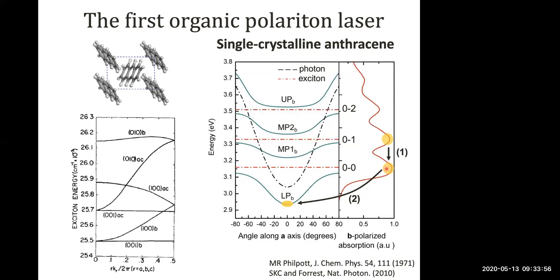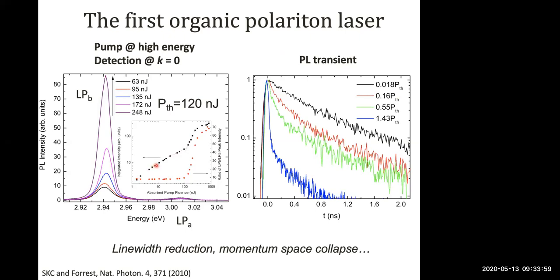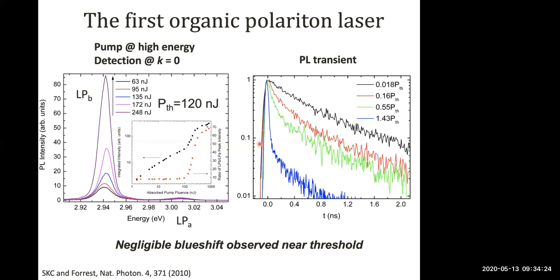And then when you pump the system at high power, you find this threshold from a sublinear regime, just because you have very, very strong bimolecular annihilation, to a superlinear regime, as well as a collapse in line width, a collapse in the k-space distribution, and a collapse in the lifetime once you cross threshold. An interesting feature in anthracene, which is rather unique to the system, is also the fact that when you cool, so all of this is at room temperature, when you cool down, you have also a drastic reduction in the lasing threshold. And then the other thing I didn't mention is that for anthracene, the blue shift is rather negligible. So as we cross threshold, we have only a tiny blue shift, less than a line width. So interactions seem to be relatively weak in this system.